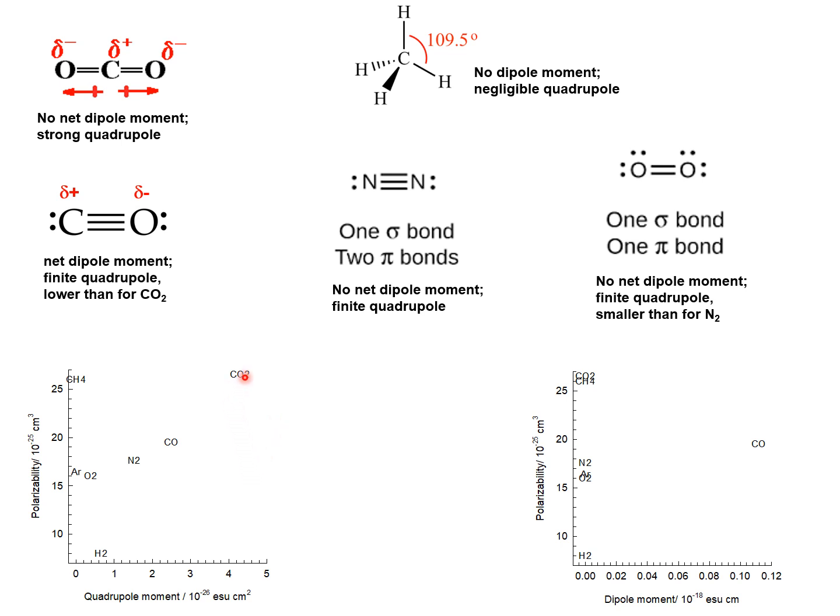For separating CO2 from methane, we can exploit the large difference in the quadrupole moments between CO2 and methane. Methane has a 0 quadrupole moment, whereas CO2 interacts strongly by electrostatic interactions with the extra framework cations.